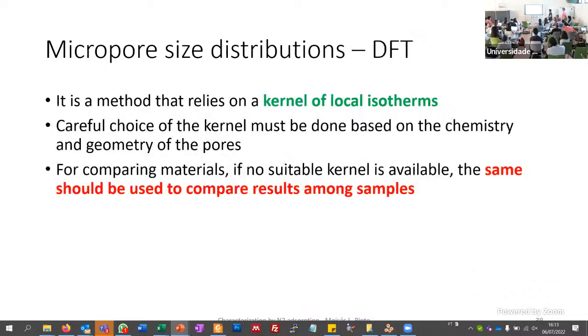So, one of the most used ones is the DFT method. DFT method not in the sense that, for instance, Richard is using. This is a numerical DFT. So this is a density functional theory, but functional of what? Of the density, but the density of molecules inside the surface, not the electron density. Yes? But nevertheless, it will give a certain kernel of isotherms, and then we can calculate the pore size distributions.